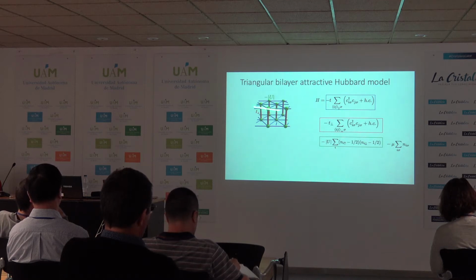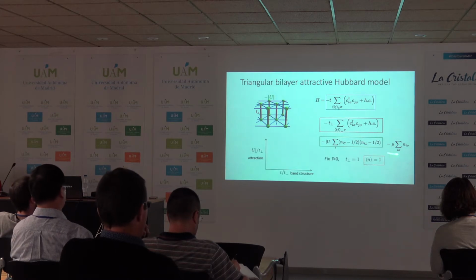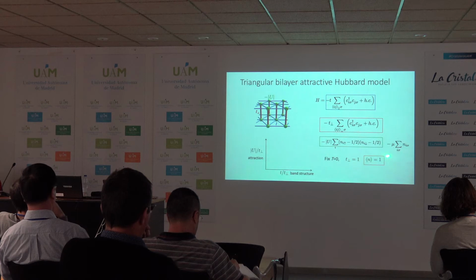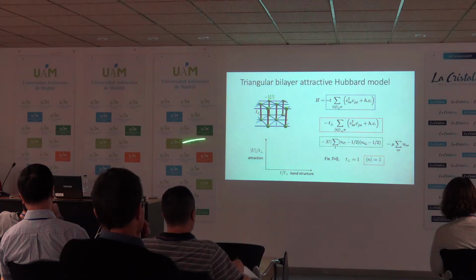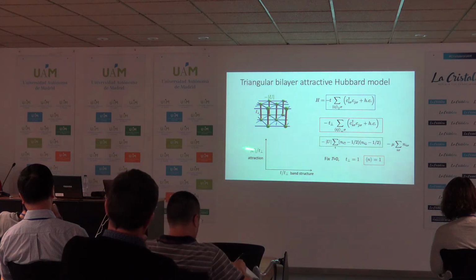So here is a hopping on a layer controlled by the energy scale t. There's a hopping between layers on these rungs controlled by t perp, and U is the attraction. And I'm going to work at a filling of 1 electron per site. And the reason for that is I want to stay in a band insulator. So here is my phase space that I would like to fill up. I want to get all the phases here. This is the attraction in units of t perp. t perp will set my energy scale. And this is the hopping in units of t perp, hopping within the layer.